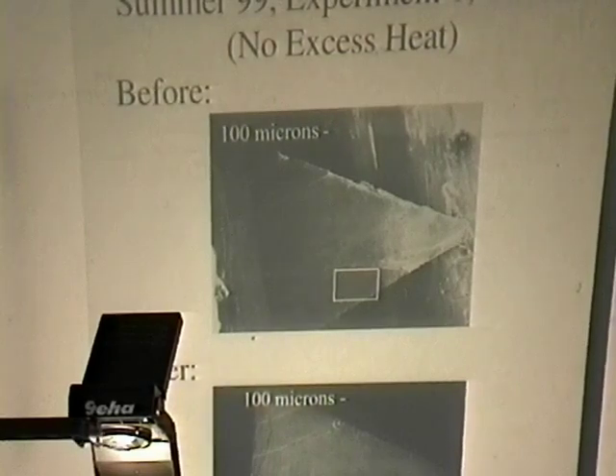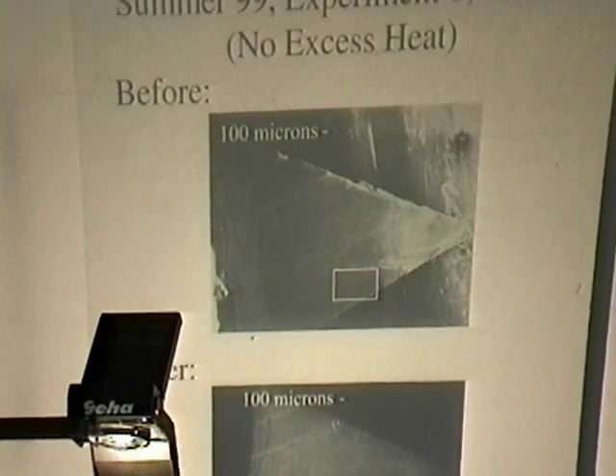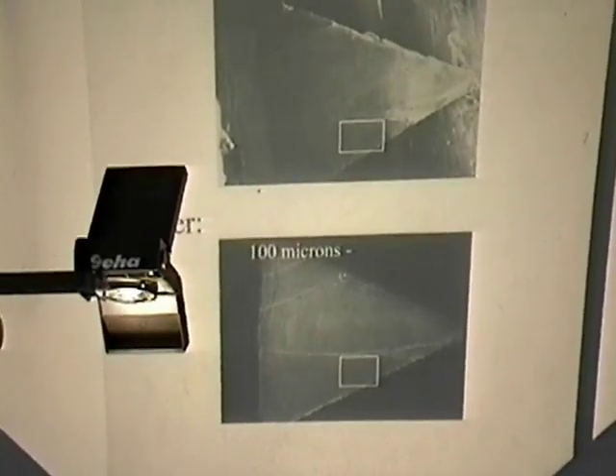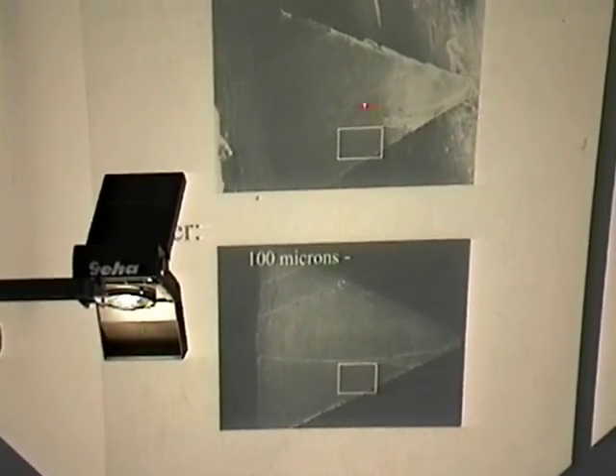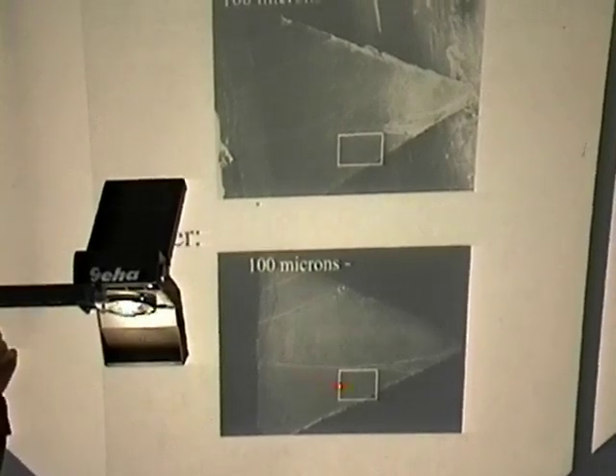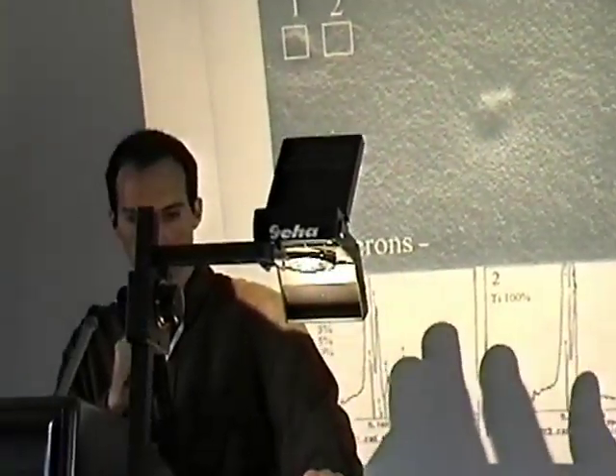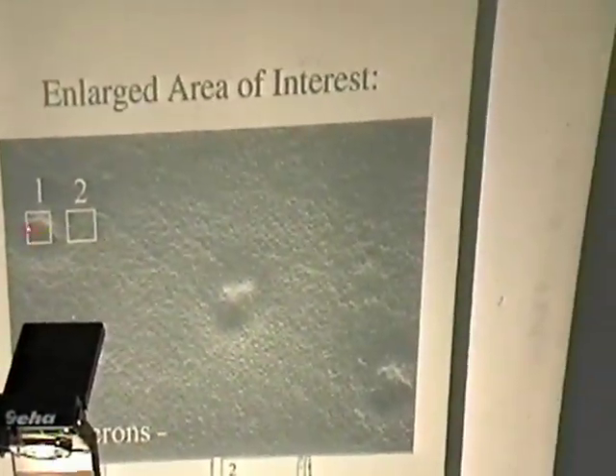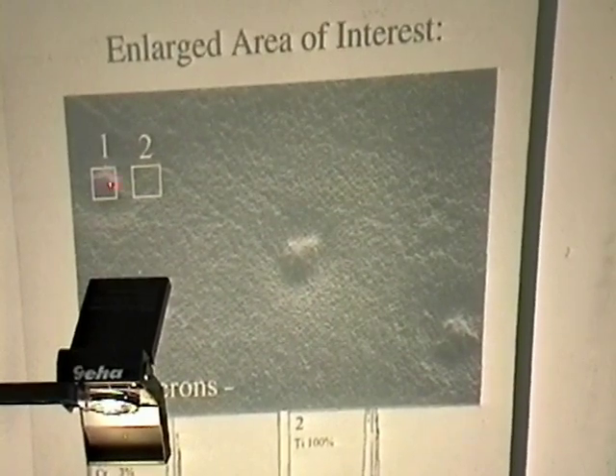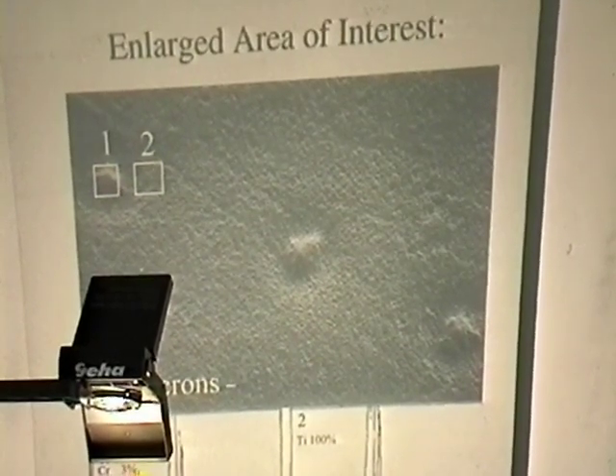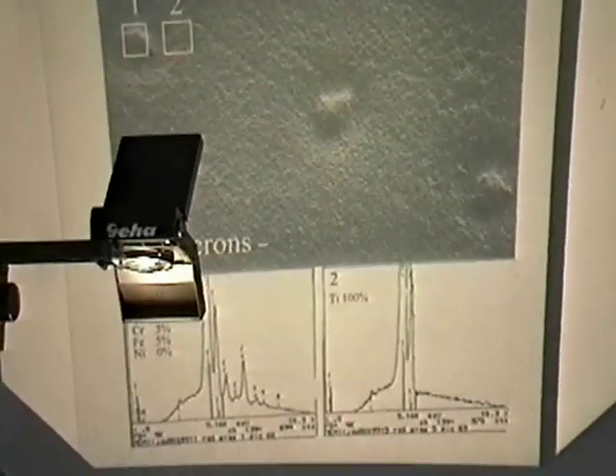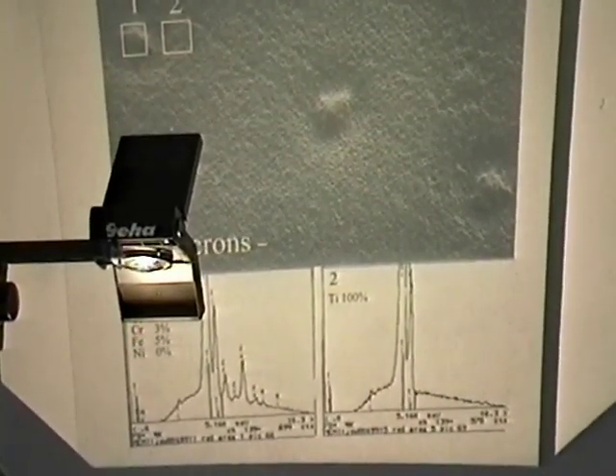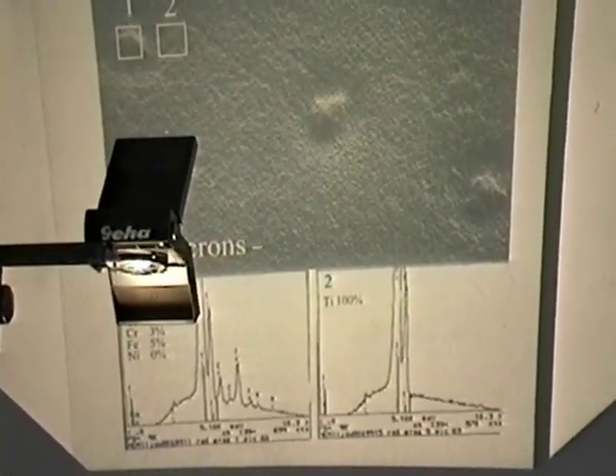Here, this is not very visible due to the slide, but there are 3 little dots. This is going to be the last picture I show. 3 little dots after the experiment. There is no excess heat on this cell. There are 3 little dots here that were not here before. I'm going to show you an enlarged view of that. And I thought I'd end the pictures with this. Here we took a spectrum, and there was 3% chromium, 5% iron, and a trace of nickel, and the remaining is titanium. Whereas if you go next door, it's 100% titanium.